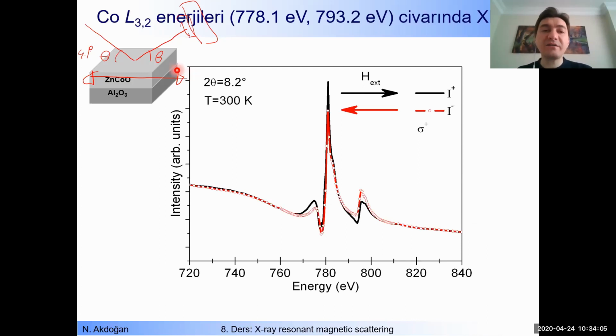Then I reverse the direction of the magnetic field, shown by the red color. Then I scan the same energy range again. So what do you see here? That the intensity recorded under reversed magnetic field is different, especially around L3 and L2 edges of cobalt material here. You can see huge differences here.